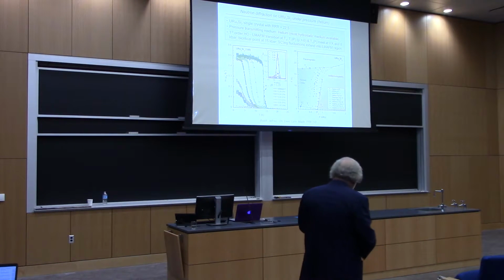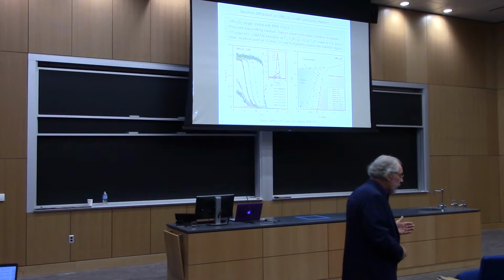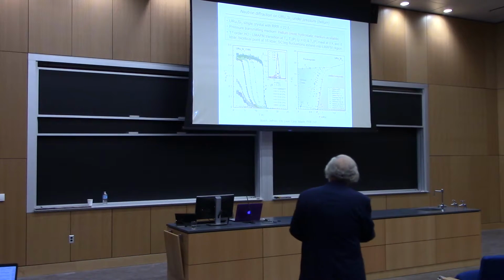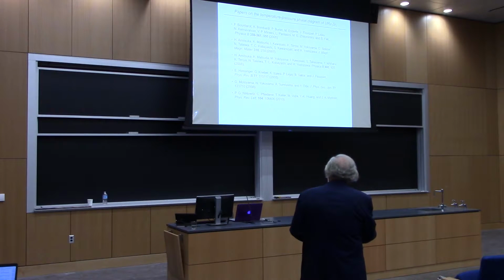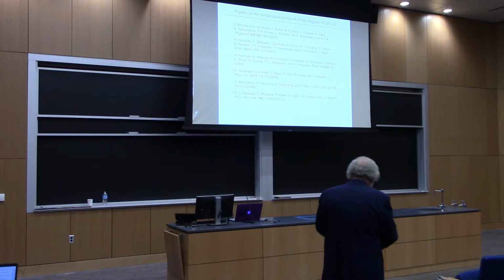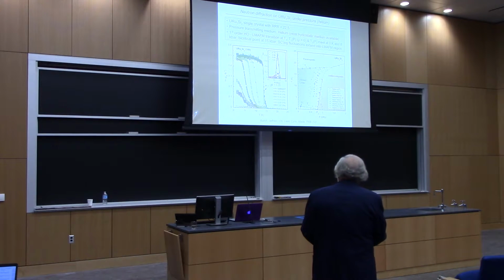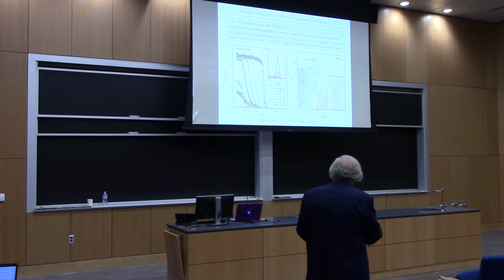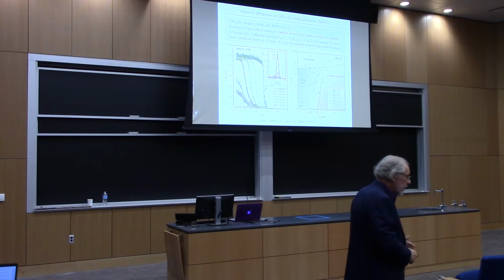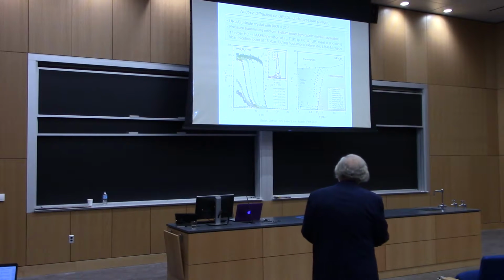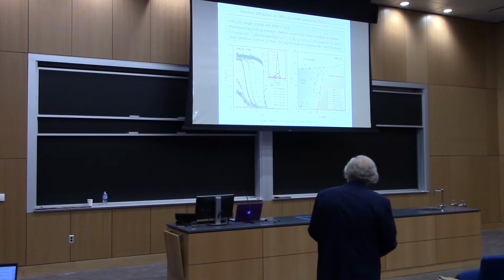And this phase diagram was observed much earlier by many people, so I don't want to give you the impression that this was the only work. There are a whole series of works done in establishing that basic phase diagram, but I think because of the pressure media that were used for neutron scattering, lower pressures were found for the phase boundary, and I think this is probably the appropriate phase boundary, the pressure for it, but the phase diagram is basically the same as ours. And let's see, this is the first order line, first order transitions.